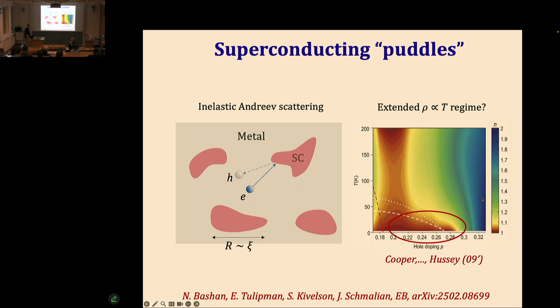Inelastic electron scattering, people see low energy charge fluctuations as well. I would argue this is probably not due to spin fluctuations. In thallium cuprates, there's a very similar behavior and no low energy spin fluctuations in the overdoped regime. So another question is how to identify these puddles.